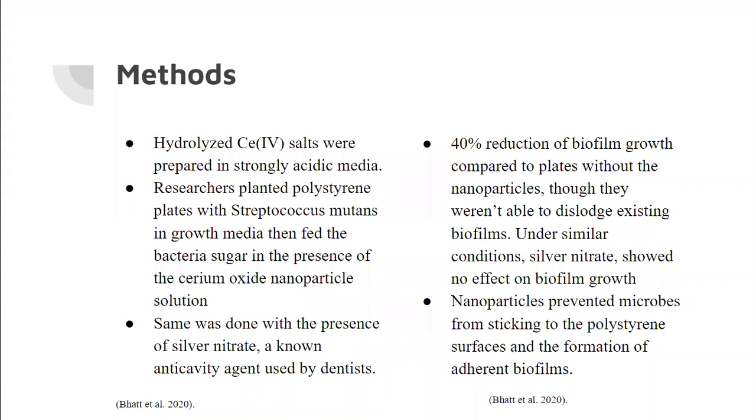The methods that were used. Hydrolyzed Ce4+ salts were prepared in strongly acidic media. Researchers planted polystyrene plates with Streptococcus mutans in growth media, then fed the bacteria sugar in the presence of cerium oxide nanoparticle solution. The same was done in the presence of silver nitrate, a known anti-cavity agent used by dentists.